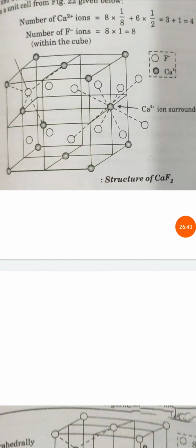But actually the coordination number is 4 and it has a tetrahedral structure. Similarly, in the case of cadmium sulfide and zinc oxide, the predicted coordination number on the basis of radius ratio value is 6, but actually the coordination number is 4 and the structure is tetrahedral.